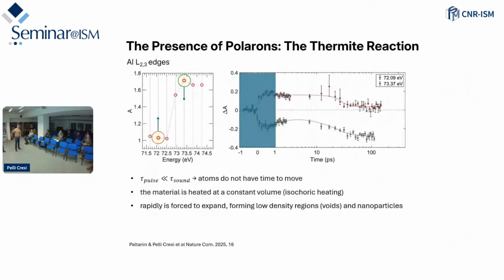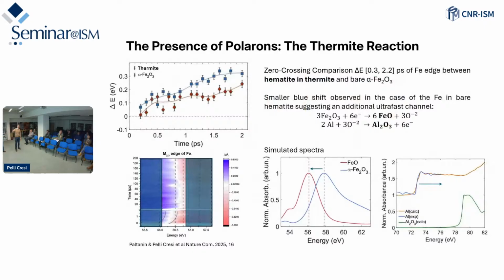So the blue shift was the one that we observed. The higher blue shift was the hematite one. Okay, the blue one is the hematite. So this delta E is just the variation from the start of the excitation to the final part. This shift is higher for hematite and lower for the thermite. So probably what happened is that you have deformation also in the thermite from the polaron, but this blue shift is contrasted by the red shift due to the formation of FeO. So when you reduce the hematite, you have a red shift.